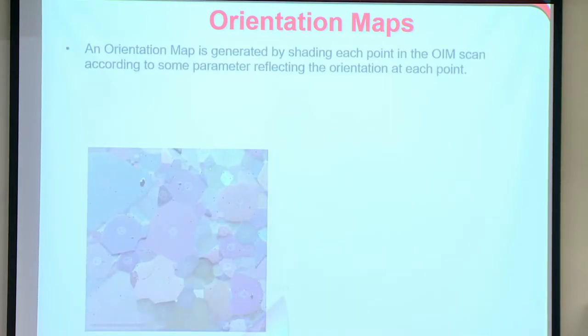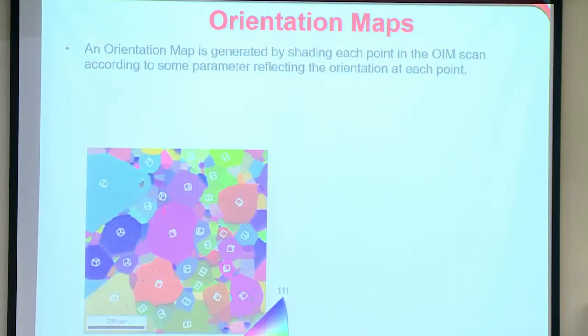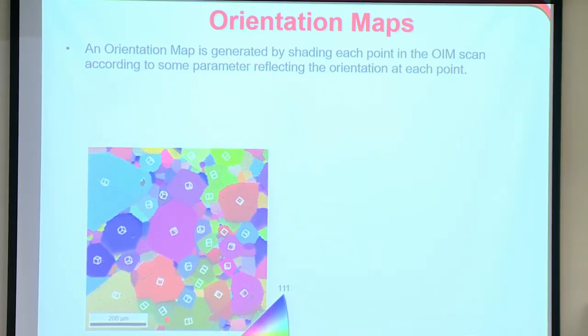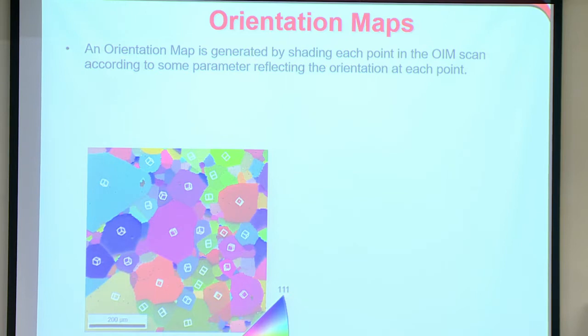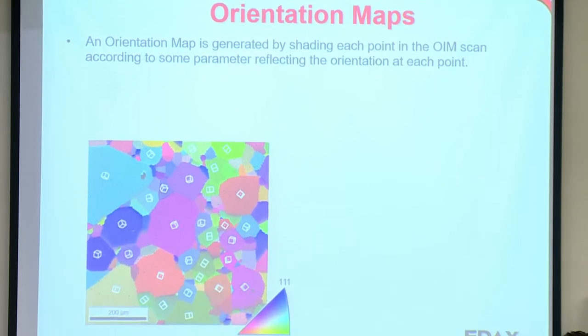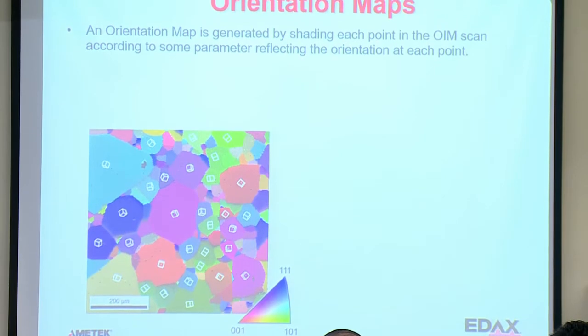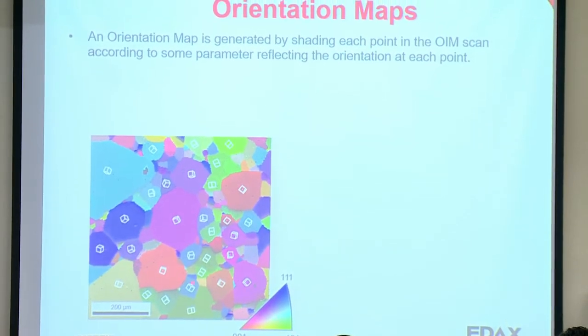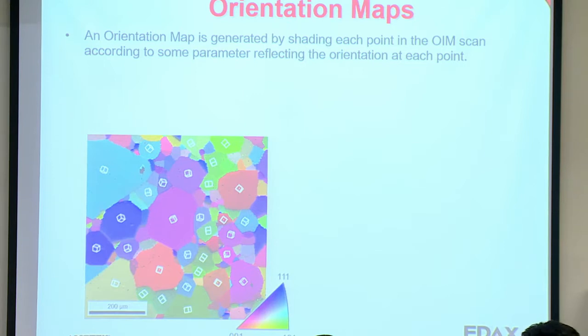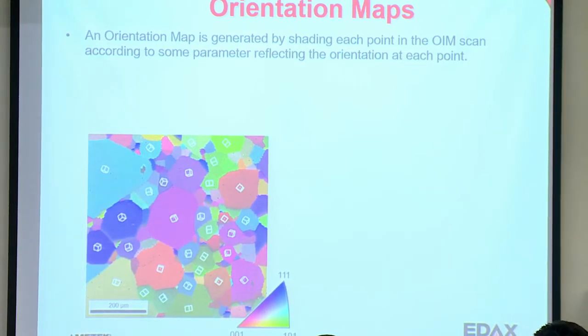The most interesting, I think, is the orientation map. We color the grains according to their crystallographic orientation. In this case, the blue ones have 111 axes coming out normal to the screen, and that's the 111 here. The red ones are 001s. You'll see here, there's a nice 001. Where's a really nice flat? There's one right here. So you have the face of the cube parallel to the sample surface. 110, you have an edge of the cube parallel to the sample surface. So this tells us the orientation of the crystal at each point.